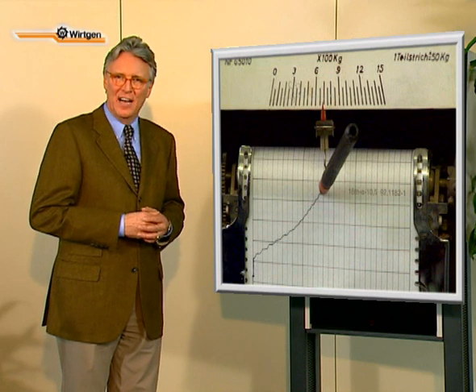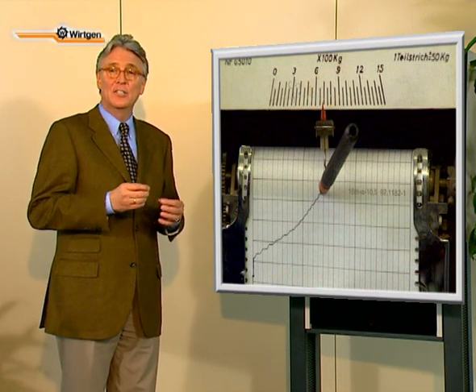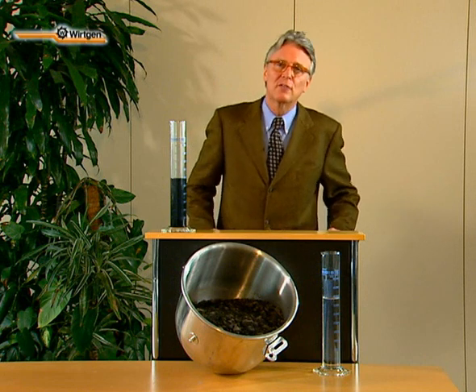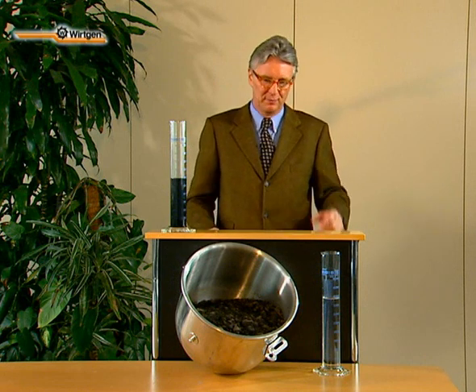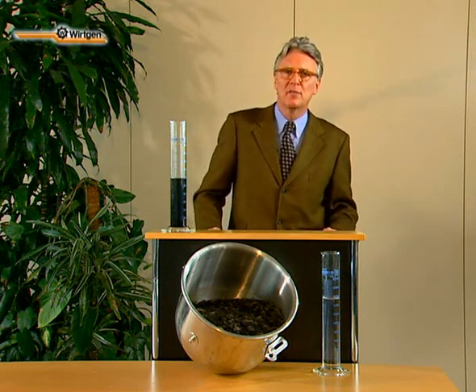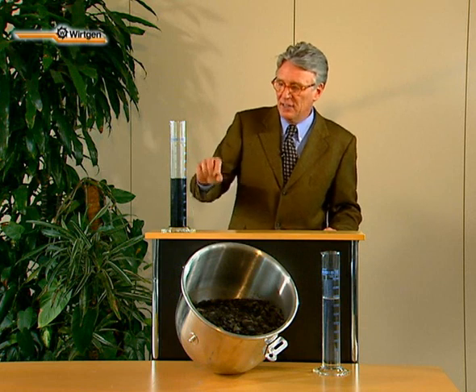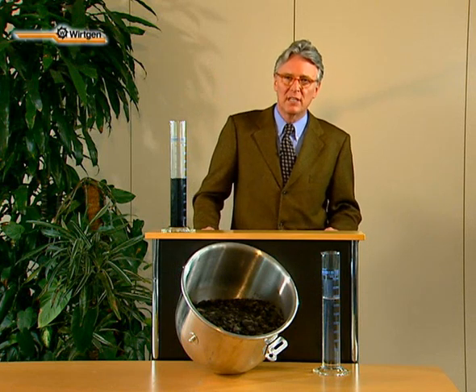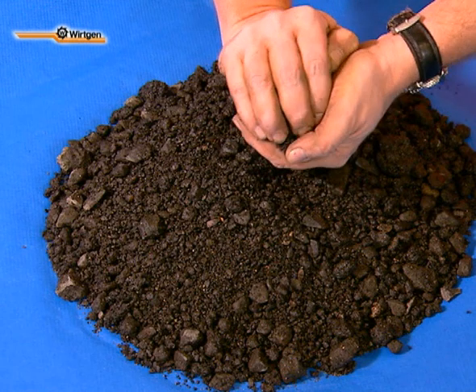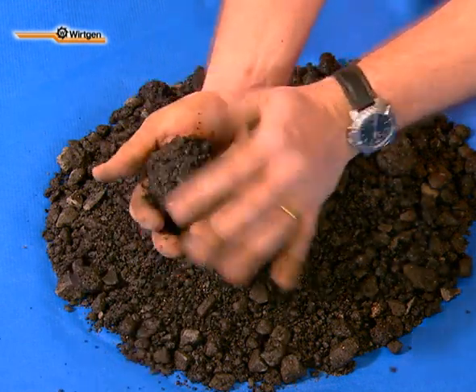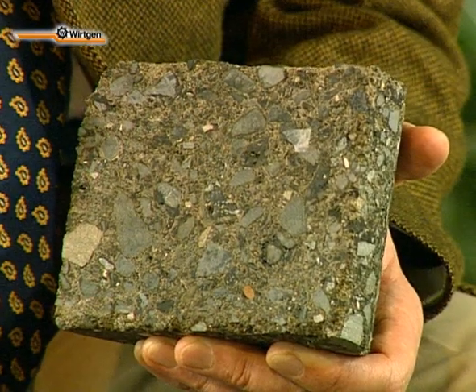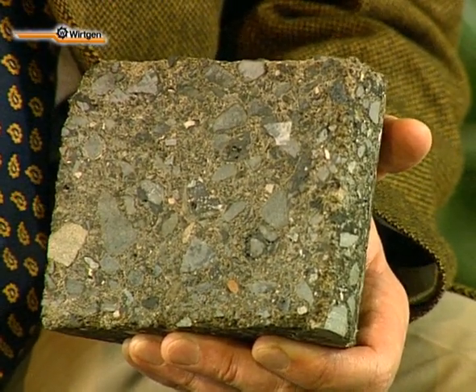There's one important question we haven't answered yet: how does this foamed bitumen actually work as a binding agent? In our example, milled material is the source material consisting of 15% filler by mass. 4% of water are added to achieve optimum compaction moisture. And 3% of bitumen in the form of foamed bitumen are sprayed and subsequently mixed into this material. As you can see, the mixed materials bind together excellently. The lab assistant is able to form this mix into a firm ball. A cross-section of the test specimen shows how perfectly the different components are bound together.